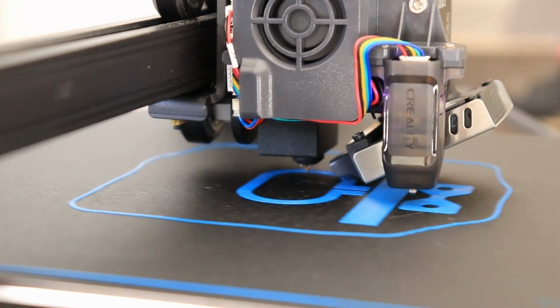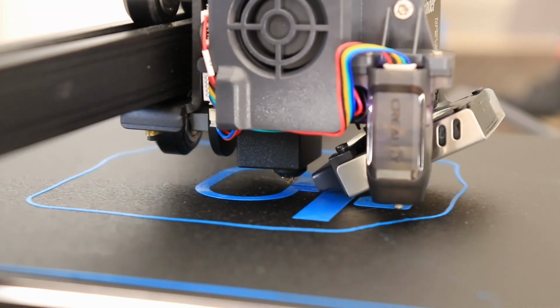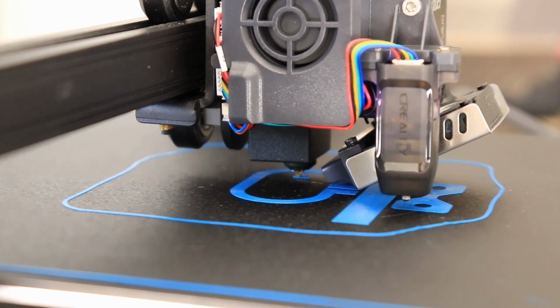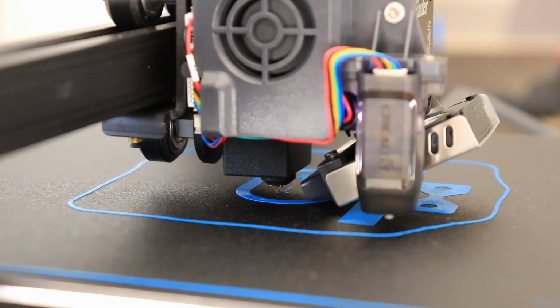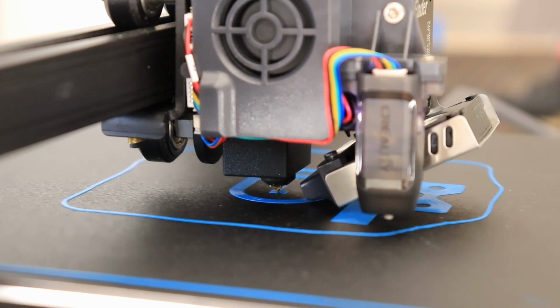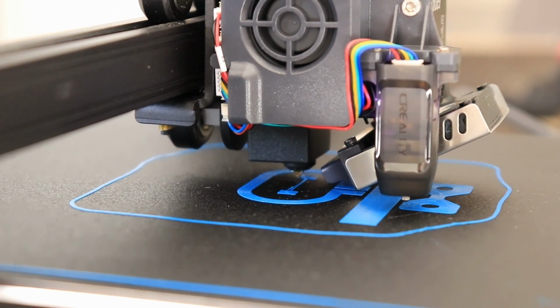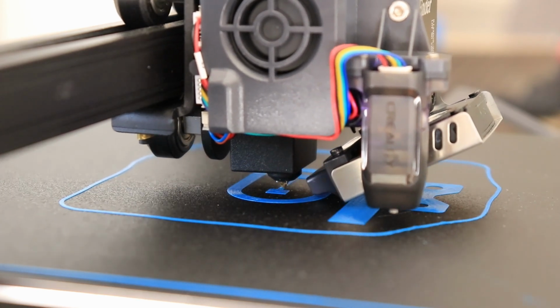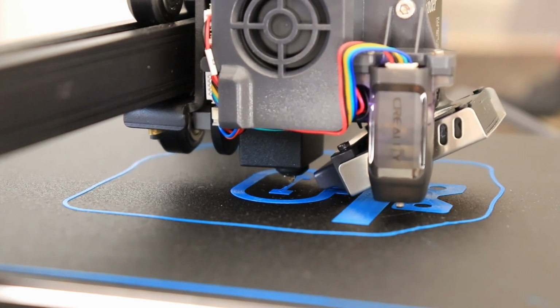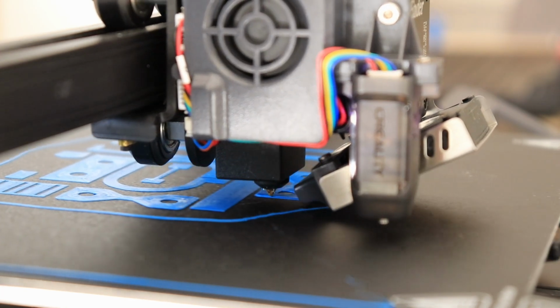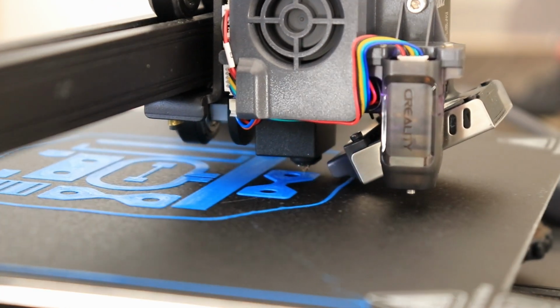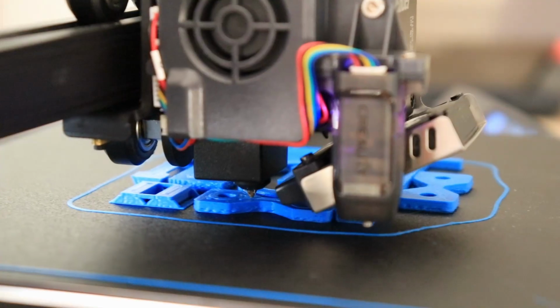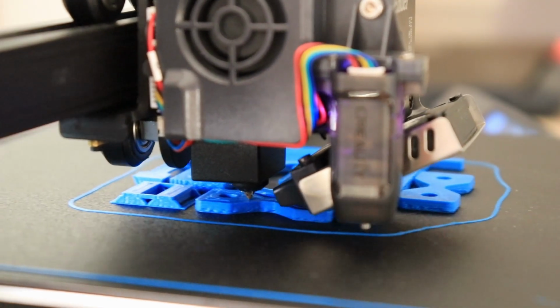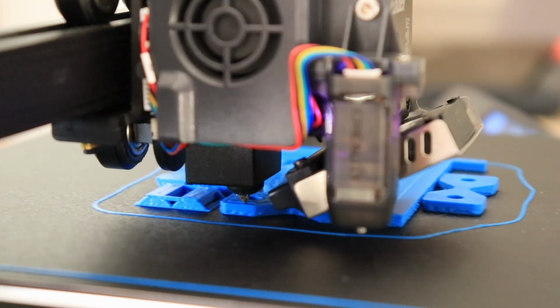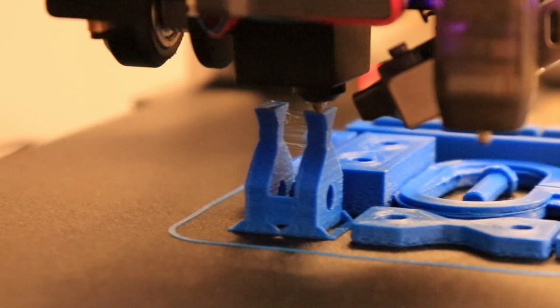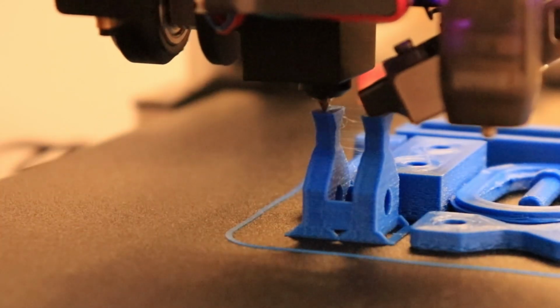And since printing of the temperature tower went so smooth, I decided to print all test objects at once, and this will be approximately 5 hours of printing. And I'm printing these test objects on 225 degrees Celsius, and the bed temperature is 90 degrees Celsius, and the cooling is reduced to 60% max. And the first layer laid down perfectly, so I hope I don't have to supervise it all the time, because I have to leave for 2 hours now. After 2 hours, printing is approximately at 50%, and it looks okay so far. And last 2 elements printed vertically for the layer adhesion test.